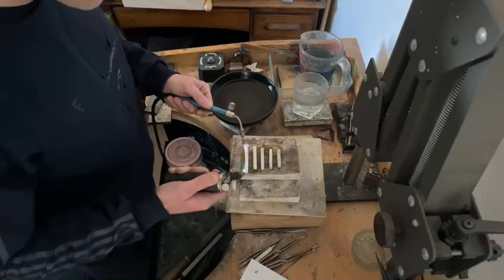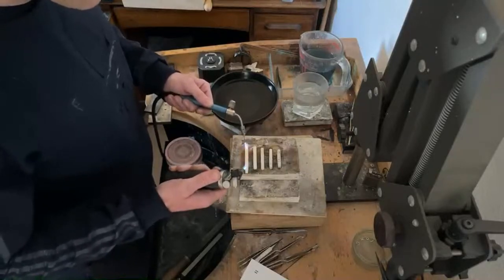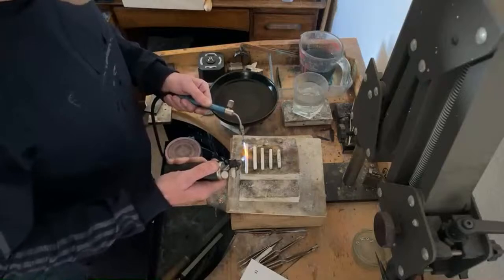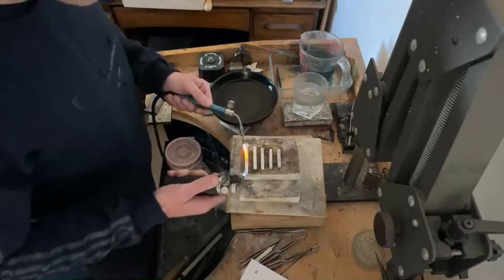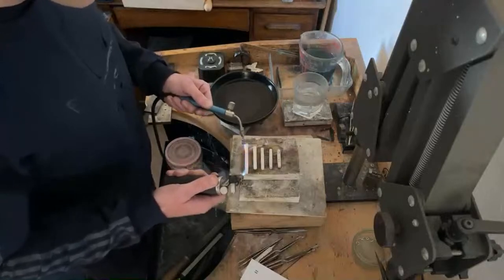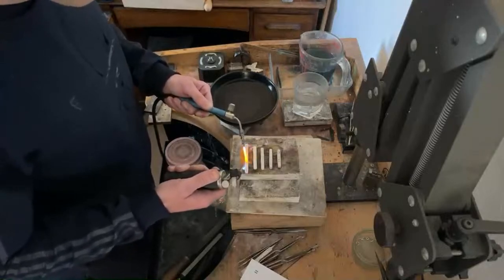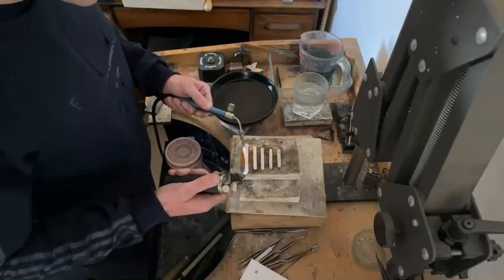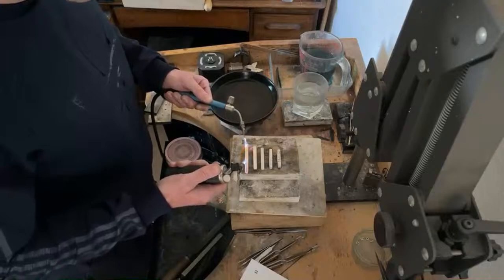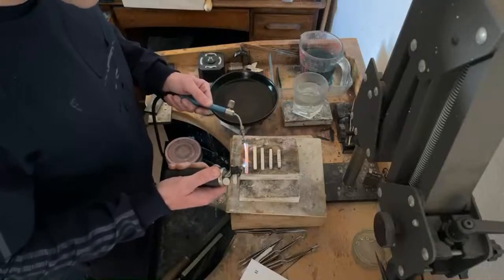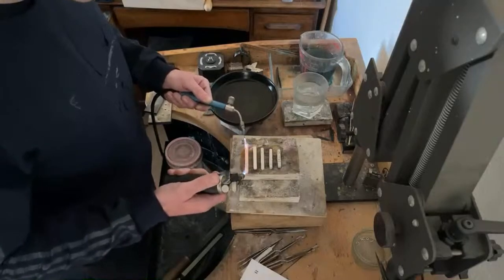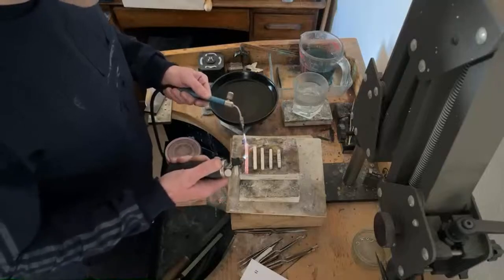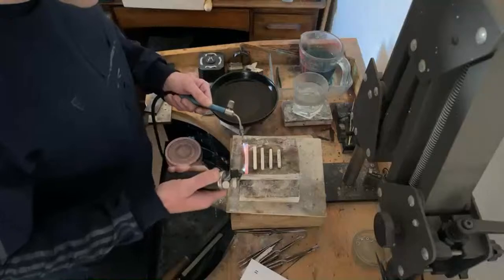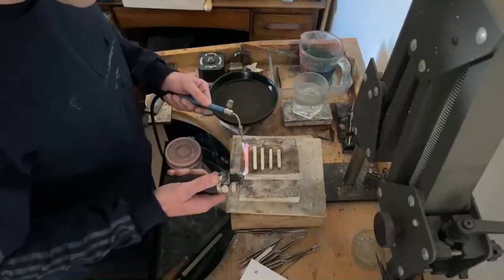We're not talking precious metal clay porous, but there's definitely something going on with porosity. And it's worse if you don't peen them, especially silver. Gold's not so bad, but with the silver, because of the porosity, if you quench them when they're red hot, when you put them back through the rolling mills, you get little beads of water, or worse if they've been in the pickle, it's pickle. Wringing out a sponge would be a big exaggeration, but you're effectively wringing water out of them.